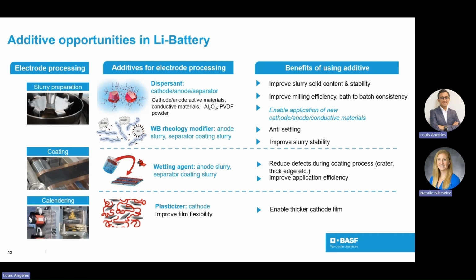Wow. Yeah, that's really interesting. There's so many different types of chemistries that go into a battery just on the additives portfolio. So in particular, how do the dispersing and wetting agents interact with active materials, binders, and the electrolytes in the battery cell? Yeah, dispersing and wetting agents are designed to improve the distribution and wetting of the active materials within the electrode slurry. And they can help to reduce the agglomeration of particles, ensuring a more uniform distribution of the active material particles within the electrode slurry. And this uniformity is critical for consistent electrochemical performance across the electrode.